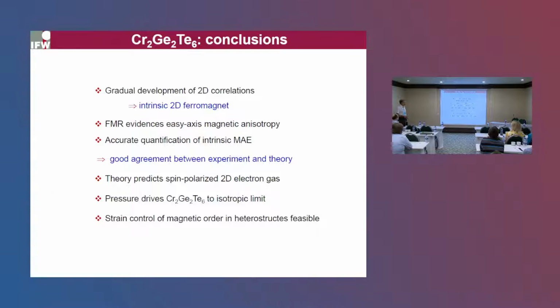And also, very importantly, we found a way to tune the anisotropy in this material by pressure, and we propose that we could have some strain control of magnetic ordering in heterostructures.